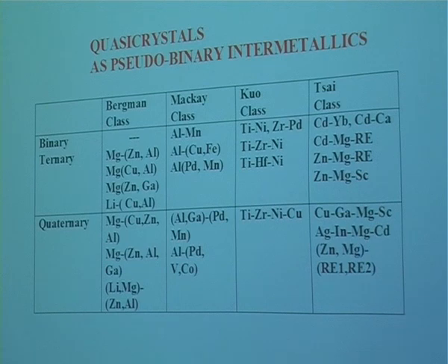But basically, as far as the structure of these four types of quasicrystals is concerned, they are the same in each one of them. That is, in the Bergman class they will have the same structure. In the Mackay class, they have the same structure. And you find that magnesium and lithium can substitute for each other. So you have lithium and magnesium and zinc aluminum. Lithium and magnesium are the large atoms, very different in terms of electronic characteristics. Yet here, the size factor seems to play an important role.